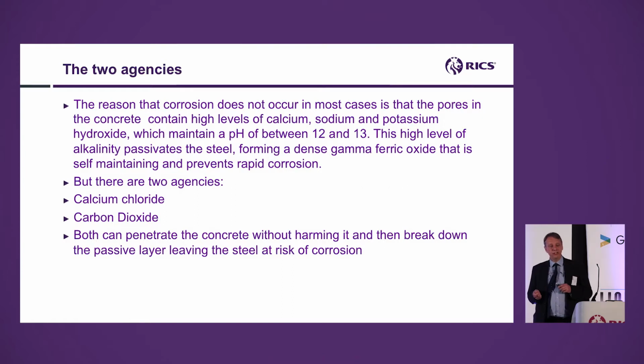The second agency is calcium chloride. And up until 1978, everyone merrily used to get their calcium chloride out and bung it in the concrete to speed up the setting time. Post 78, that's strictly taboo. And the reason for that is, if you put salt in, it creates conditions of high conductivity. And what did I say a few minutes ago? High conductivity equals potentially high corrosion rates. So the chloride will attack and disrupt the passive layer, leaving the steel vulnerable to corrosion. Chloride problems are particularly difficult to deal with, and I'm going to come back to those in a second.